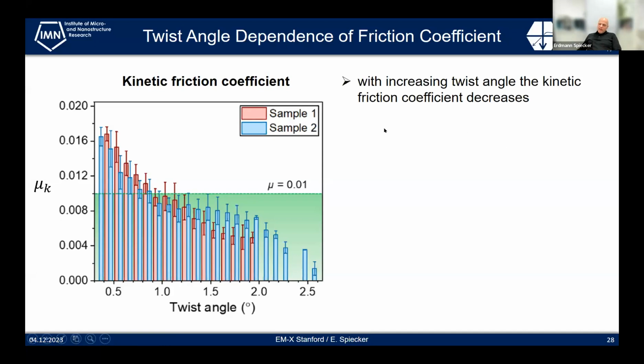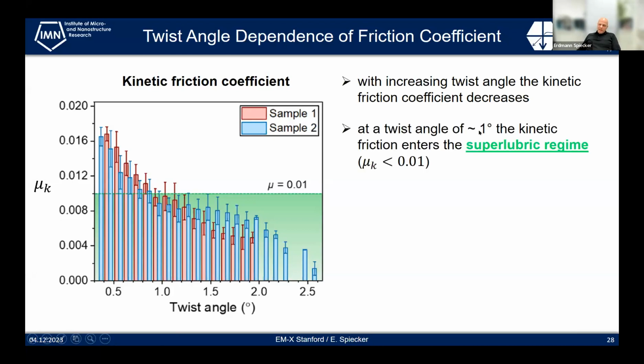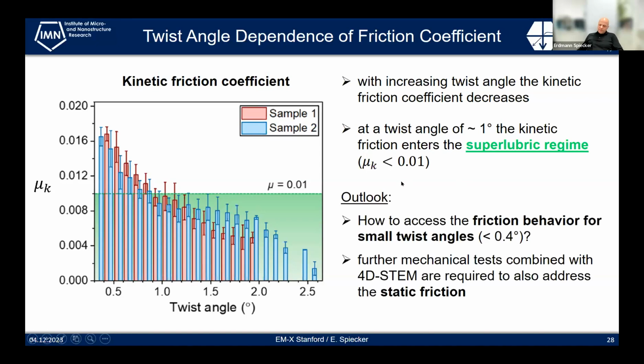So what is the outcome? With increasing twist angle, the kinetic friction coefficient decreases. At a twist angle of about 1 degree, the kinetic friction enters the superlubric regime. And what can we do else in the next step? We would love to assess the friction behavior for very small twist angles, which is particularly interesting. So what about the transition from the lock-in situation to the first sliding situation?